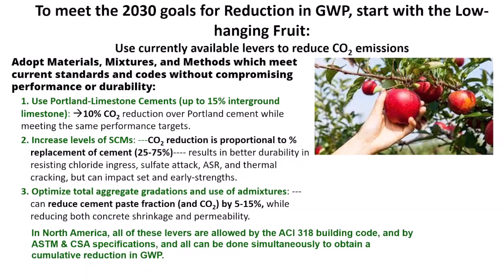They were intended to be equal performance to the base clinker for the type 1-2 cement they were replacing. They're not to be equal performance to every other cement. They were supposed to be equal in performance to the cement from the same clinker from the same factory. So if you're going to buy cement, some of the issues that have been involved with Portland limestone cement, which seems to be unique to certain parts of this country and not other countries, is that people are buying multiple sources. It may not be ever, there's issues, but like in Canada, we've been using Portland limestone cements. We're at 100% now. There was never any issue with adopting them and using them. The contractors did their base homework, and everybody communicated and got that done. Anyway, so 10% reduction from that.